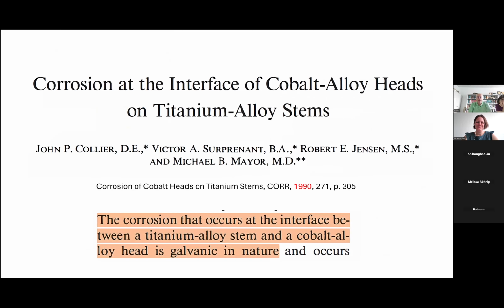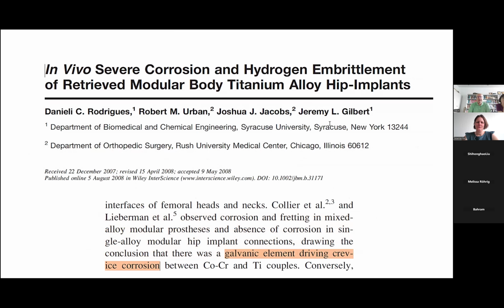If you see here, for example, one of the papers, it was published in 1990 from a group in the US, saying the corrosion that occurs at the interface between titanium alloy and a cobalt head is galvanic in nature. It was published in 90. And after, you can see here, for example, something in 2008, where we speak about crevice corrosion, which doesn't exist in orthopedics, at least on the old hip and knee joint. But they start to speak of galvanic elements driving crevice corrosion. And I am very sorry, it is wrong.